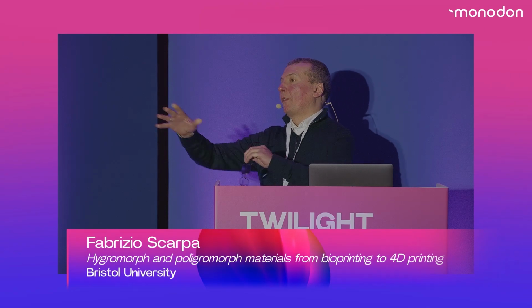So you turn from the fiber being the main agent to the matrix being the agent. And in those cases, we have also deposited the equivalent of a PCB circuit. By Joule effect, we can increase the kinetics by one order of magnitude. Still, we are not talking about something really fast, really for a Formula One race car. And besides, that would also be illegal. But speed of actuation is a limitation.